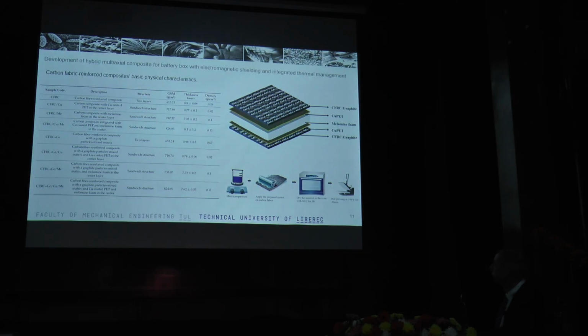I'll show you the combinations. We created 8 combinations of these materials. First one: only 2 layers of carbon. Second one: 2 layers of carbon and a middle layer with copper. Third one: 2 carbon layers and melamine foam, which was there for insulation. The final one was the full set: 5 layers—carbon, copper, textile, melamine, and again copper and carbon.